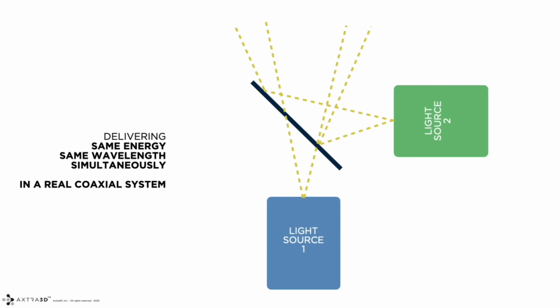What does it mean? That again, using a very specific behavior of the light, we are able to deliver at the interface the polymerization under the VAT in this case, but it's extremely clear that our technology and our light engine can be used for both top-down and bottom-up systems with different wavelengths, with different building areas. We are implementing a real coaxial system where our components are completely fixed, and that's the reason why we are able to combine both the sources with a resolution under 20 microns.